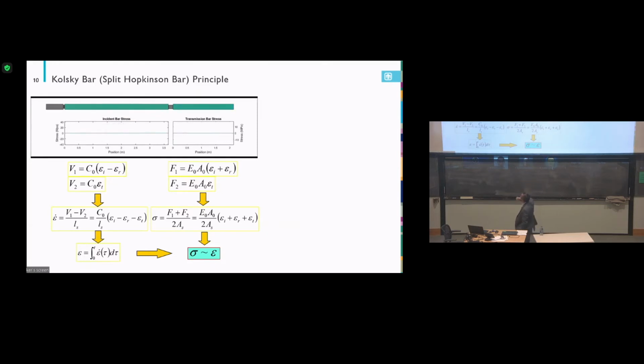We have the equations. Based on stress wave propagation, we have particle velocity at both ends of the specimen. Then we can calculate displacement, strain rate, and the strain applied to the sample, and we have the forces or stresses at both ends. So we have the stress, we have the strain, then we have the stress-strain curve, and we know the strain rate.